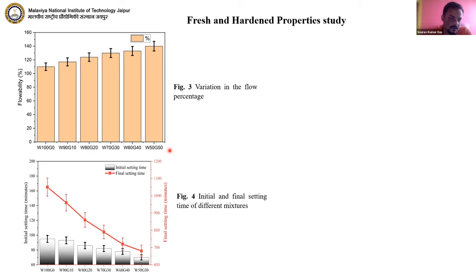And coming to the setting time, interestingly, you'll see that the initial setting time and the final setting time both get reduced when you are increasing the glass waste. Glass has a higher amount of amorphous silica, and that silica goes through a rapid geopolymerization when it comes in contact with the alkali solution. That is one of the reasons why the setting time is getting highly reduced when you are using glass waste as a waste material.